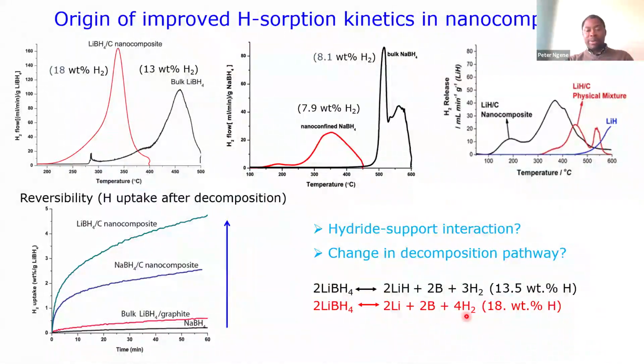And of course, there was a lot of work during that time. We wanted to really see, can we understand what is going on with this material? And that is where we started with X-ray Raman scattering. Somebody will ask why X-ray Raman scattering is very difficult, why didn't you use another technique? The fact is that most of these materials are quite amorphous when you make them. If you just nano-confine them, they have no long-range crystallinity, so you cannot just use XRD to look at the structure.